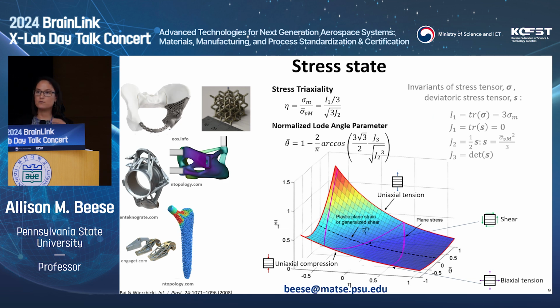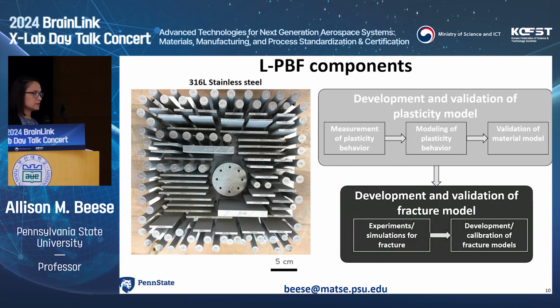So the idea is for additive manufacturing, if we have these complex shaped components that are accessing lots of different stress states, we want to know how much ductility we have in each of those to know how far we are away from failure. So we do this as a two-step process where we fabricate samples and we first study the plasticity behavior and then the fracture behavior. In both of these cases, we use a number of experiments, we develop models, and we calibrate those models so that we can understand how the material deforms and fails.